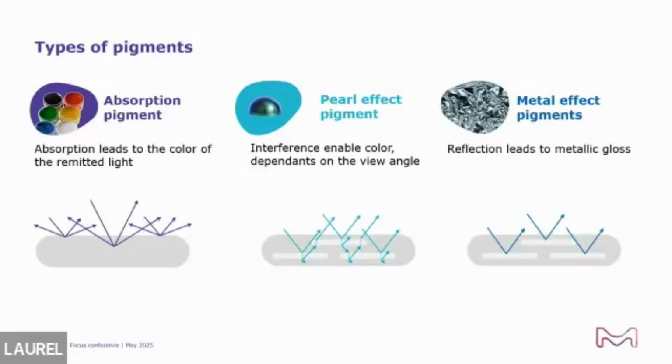For our pigment, it's very angle dependent because they're semi-transparent. Part of the light hits the flake and reflects, and part of it goes through the flake, then reflects. So the color you see is actually the interference color. Without light, you don't see any color. So our pigment definitely needs the light to see the colors.